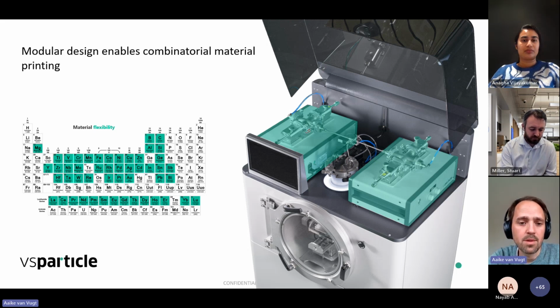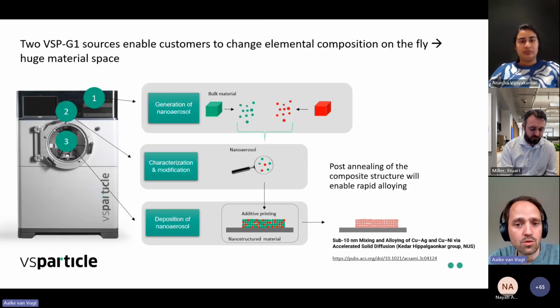The other thing is that because you are using 2 sources and we can control the output of both sources very easily by controlling the number of sparks, by controlling the energy per spark, and by that we can control the elemental mixture if we combine the outputs of both sources. So we can print a nanoporous layer where we have a predefined elemental composition between nanoparticles, in this case red, and nanoparticles green. And what we have been seeing in the past months is that if you have this composite nanoporous layer, and if you heat it up to the right temperature, you can see the formation of a new alloy material without losing your porosity.